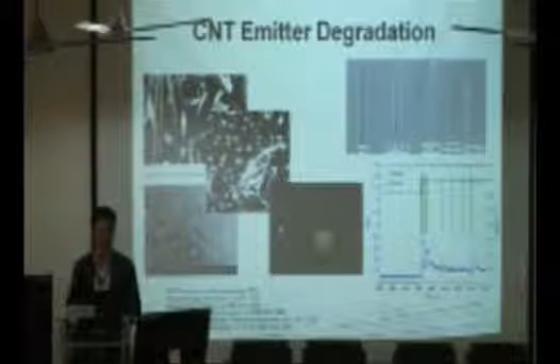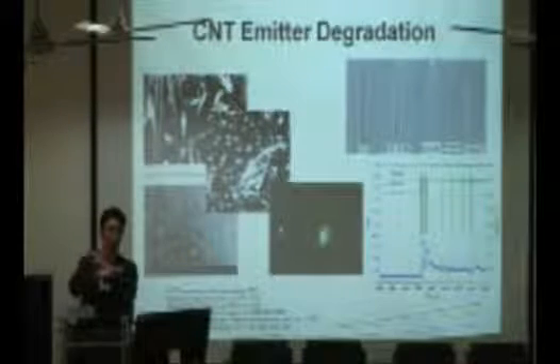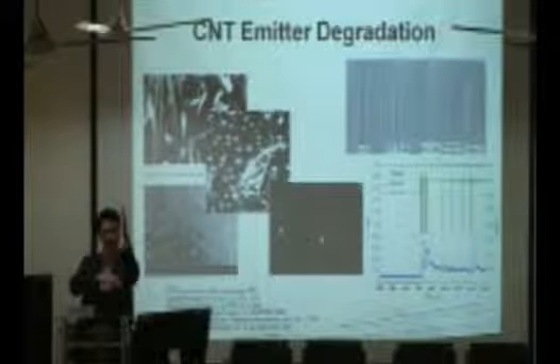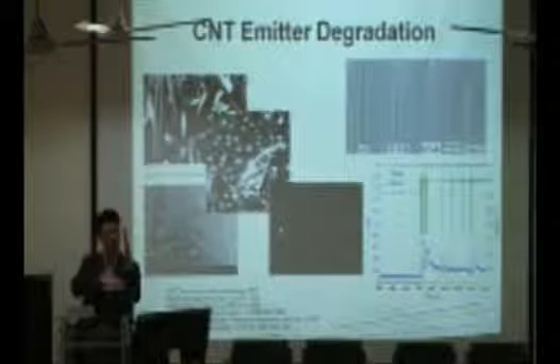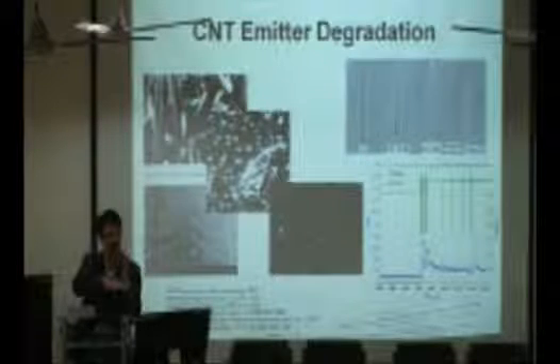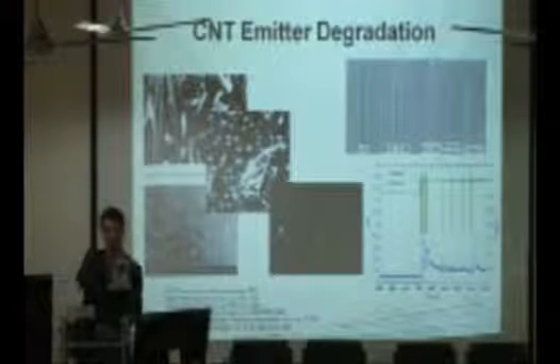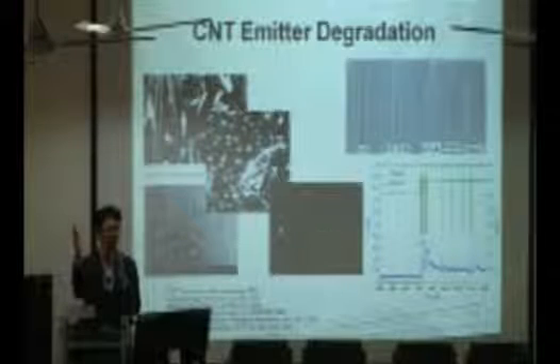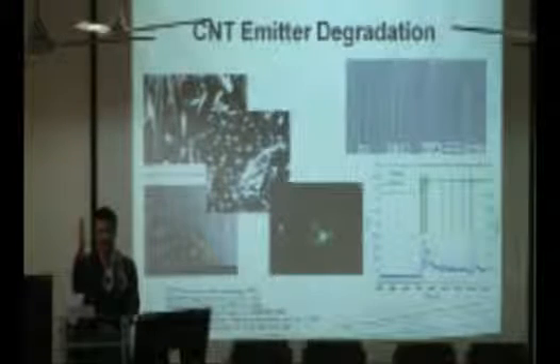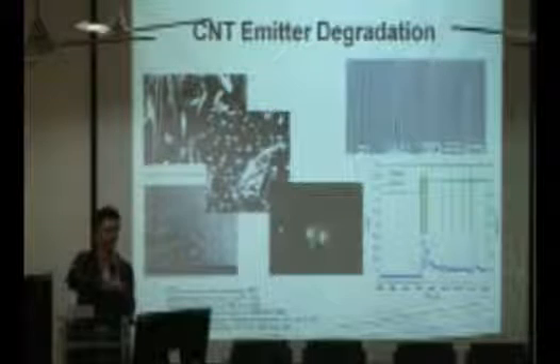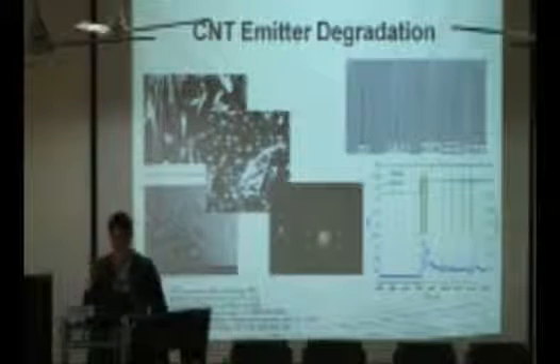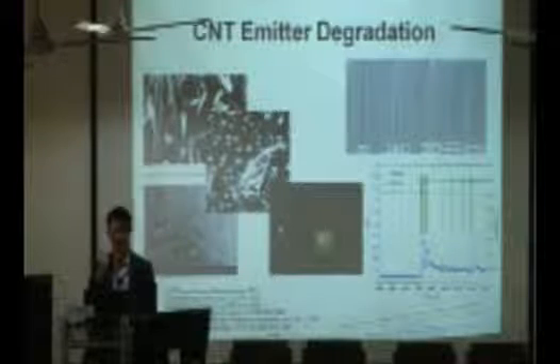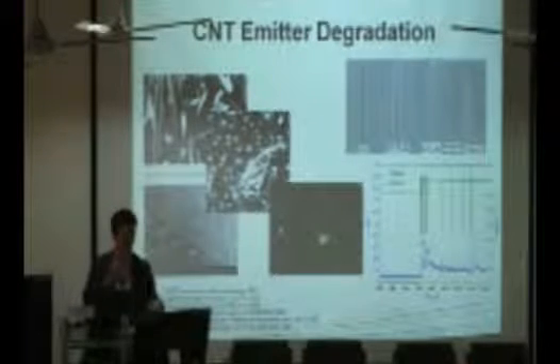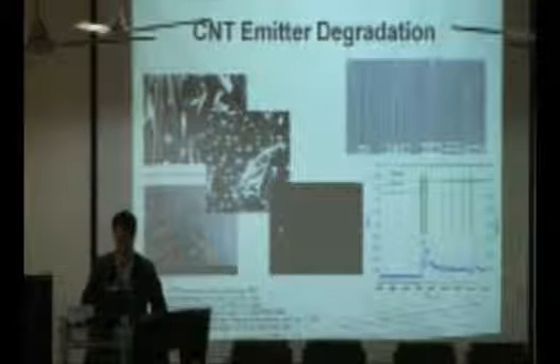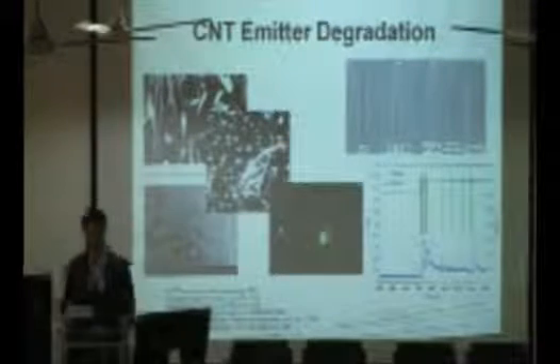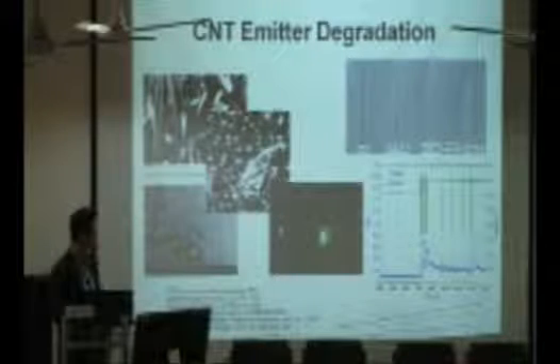The other problem is if we were to have a randomly aligned carbon nanotube, as one CNT burns off, the length is decreased by the electrostatic force interaction. A new CNT would pop up to replace it. And as this CNT burns off, new CNT would come into life and start emitting. Now, this would increase the lifetime of the emitter, obviously, because new CNT are always popping up to emit current. But the problem we face is instability in current, as you can see here.